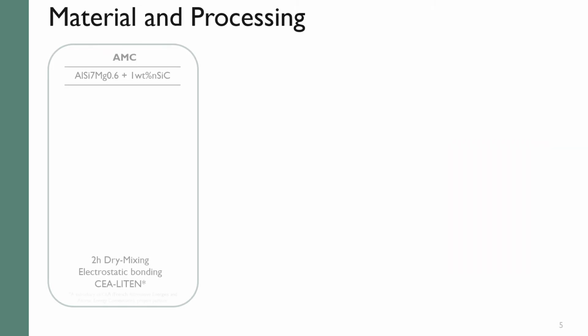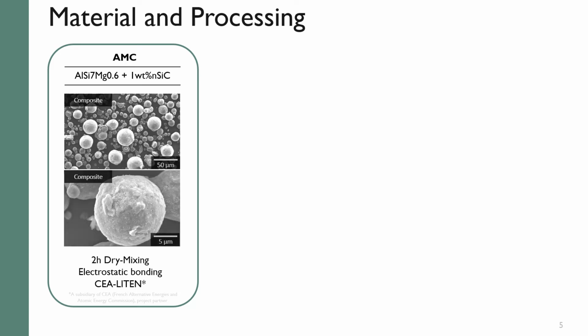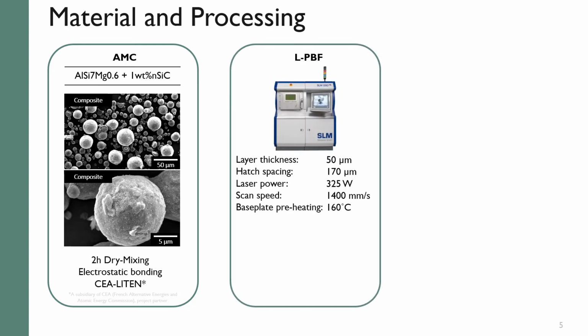In this study, we used AlSi7Mg0.6 as the matrix and mixed it with 1% nano silicon carbide to produce our composite powder. And here you can see in the SEM image nicely decorated composite powder. And for production, we used SLM Solutions 280HL with the 160°C base plate preheating. We built vertical and horizontal samples, which we will be comparing in the coming slides.